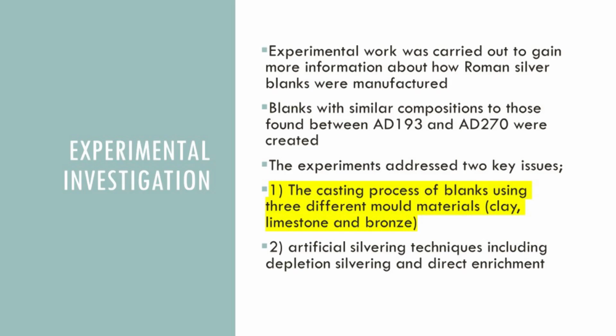Following this, experimental work was carried out to gain some information, and these experiments addressed two key issues. First was the casting process of the blanks. Following the mould survey of moulds from other ancient contexts, three potential materials were identified. These materials included clay, limestone and bronze, and all of them were tested in the experiments. The purpose was to gain practical information about the casting process and then hopefully gain some relevant insights. The second issue addressed was the artificial silvering techniques used to disguise the lowered silver content. However, this paper will only be covering the casting process.